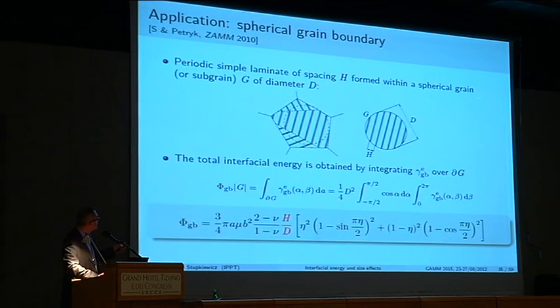What we can do is, for instance, we can look at the grain. Imagine you have a spherical grain, which is an approximation of an actual grain or a subgrain in a material in which there is a periodic laminate. And then if you want to know the interfacial energy of this kind, at the boundary of this spherical grain, we just integrate. It's not that difficult. The gamma E grain GB, this is the energy into which we plug our approximating function, and here we get the result. And now it depends on all the parameters, like eta, nu, but no longer on beta and alpha. And it depends also, of course, on the ratio of the spacing to the diameter. So there you immediately have a size effect, a size-dependent energy contribution. Okay, so we will use this formula later.